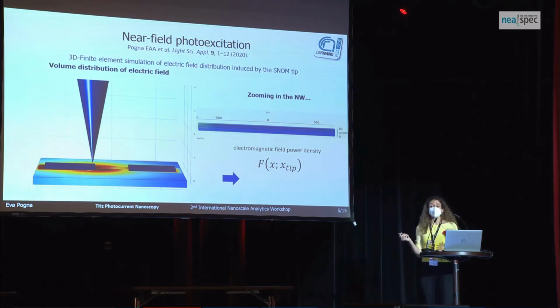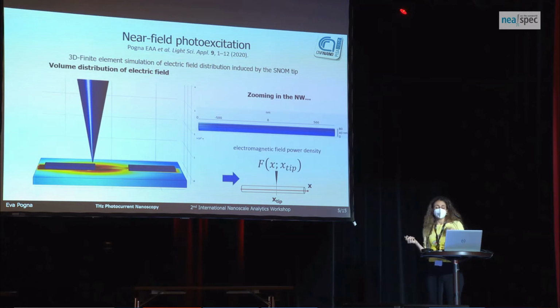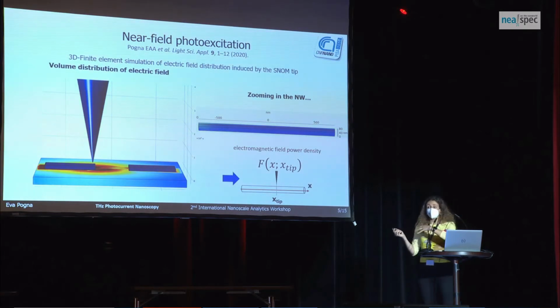I would like to convince you that near-field photocurrent is a powerful tool for distinguishing these different mechanisms. We simulated the effect of the illumination with the AFM tip of the nanowire. You can see a 3D finite element simulation by COMSOL Multiphysics. Sorry, there was a movie, okay. We actually evaluated what is the field distribution across the nanowire as we scan the tip.